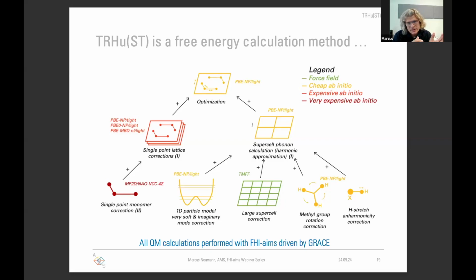And then in the vibrational branch, of course, we also do supercell phonon calculations. So we sample the Hessian matrix by atomic displacements, construct the dynamical matrix, and solve for the phonons. And that can be done in principle with FHI-aims for relatively large supercells, but that would be way too costly, because please keep in mind our methods have to work, depending on where you are in the crystal structure prediction funnel, for billions, millions, thousands, or at least hundreds of crystal structures. And so whenever we do a CSP, we need free energies for 100 crystal structures and not only for one. And so what we do has to be inexpensive just as well as accurate.